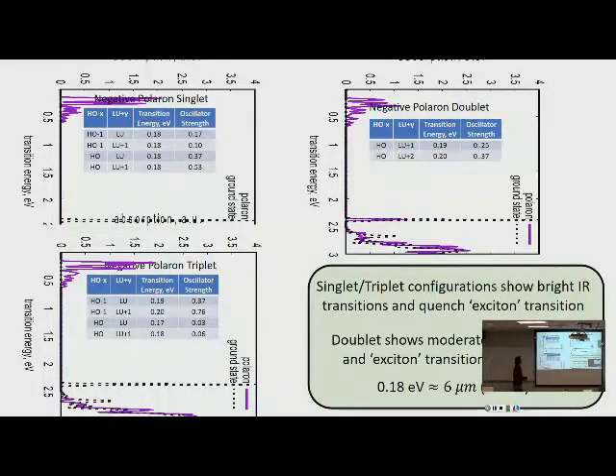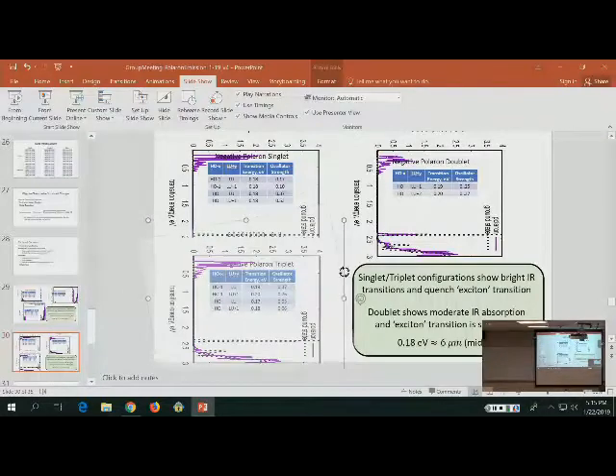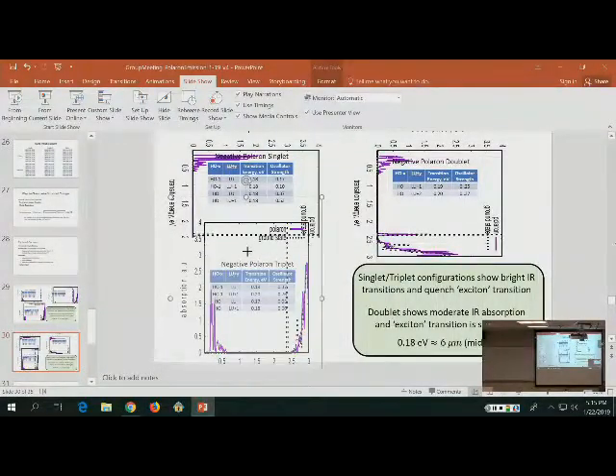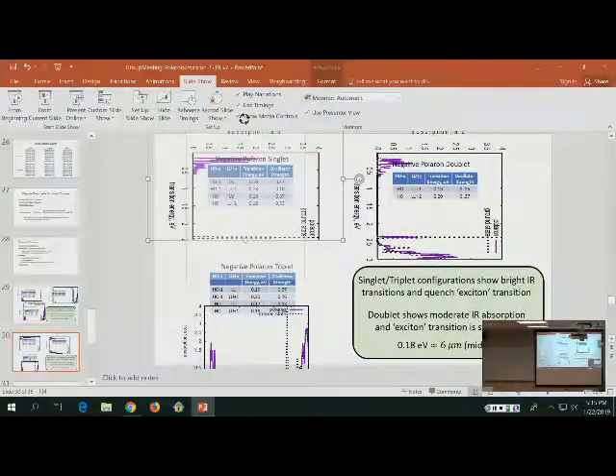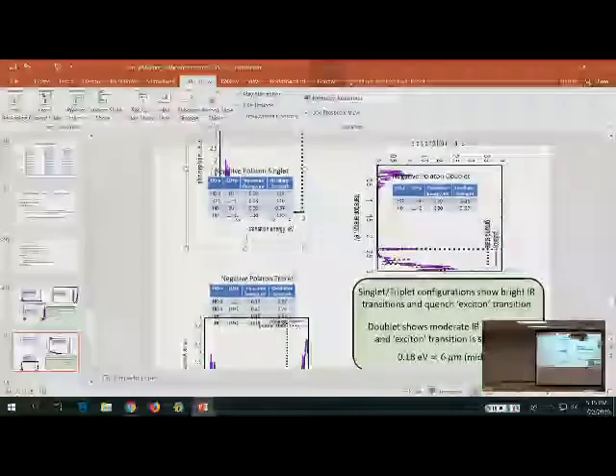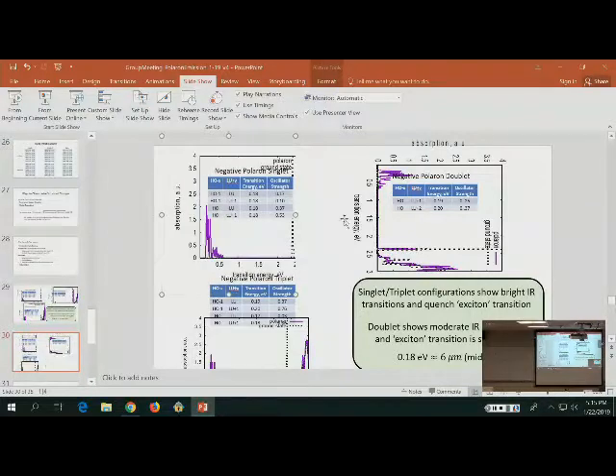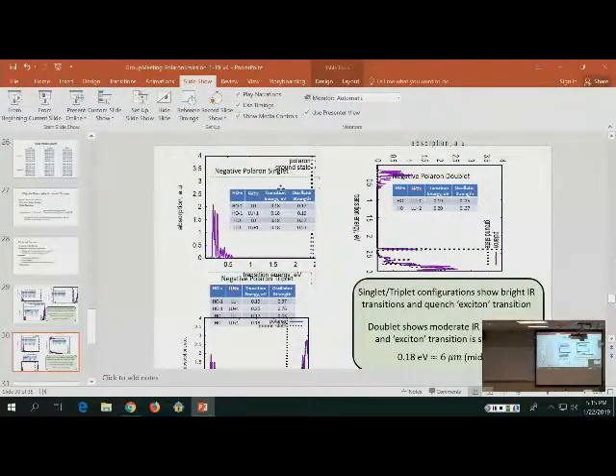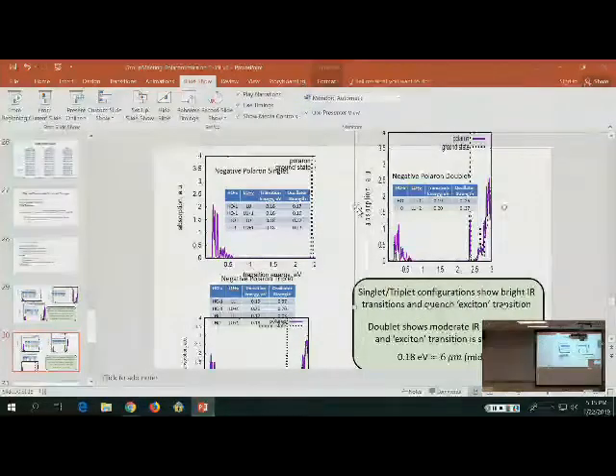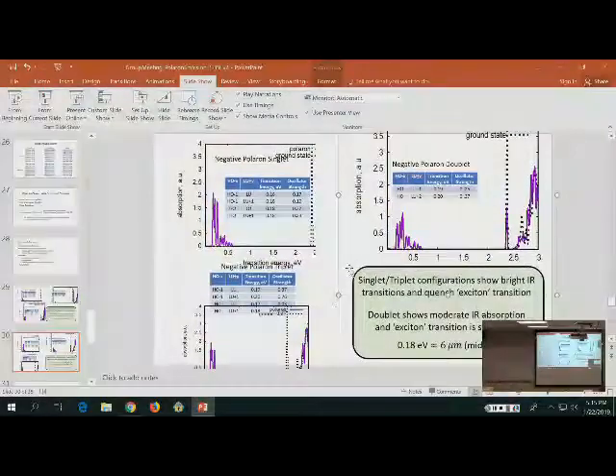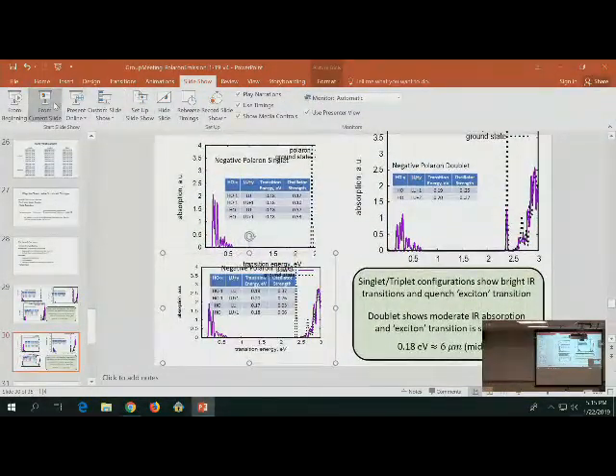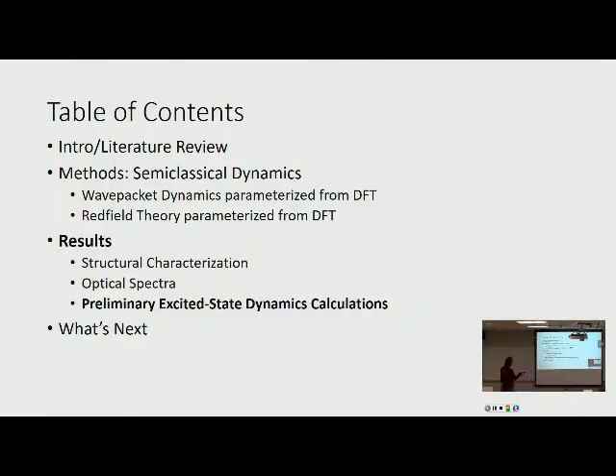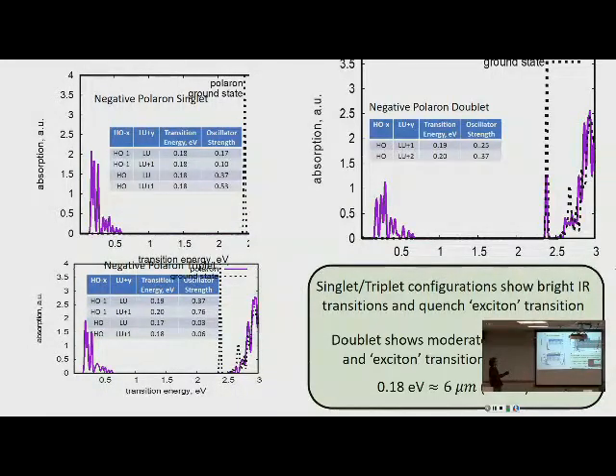And the negative Polarons picture is a little bit better. They all show pretty bright IR transitions, and the energy gap's a little wider for the negative Polarons, like 0.18, 0.2 eV. That corresponds to about 6 micrometer IR, so that's mid IR. That's even better than the conventional materials I talked about earlier. Maybe one of them got out into that region. And they all have pretty bright oscillator strengths for those transitions, or they're at least all above 0.1 in the 0.1 to 1 region.